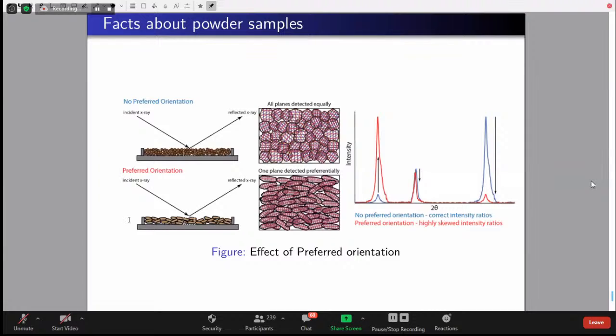But because here you could see the crystallites are not ground well, number one. Number two is they all are arranged in one particular fashion. Then they will give the peaks completely in a different way. And if you turn this sample another 90 degrees, you will get another peak more intense. So every time people load it, you will get different results. That is because it has a preferred orientation.